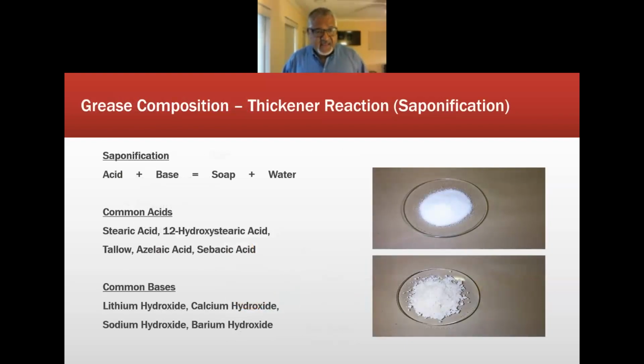Basically, I just want to describe the saponification process. You add an acid plus a base, and you end up with a soap. Oh, look, there's water as a byproduct, then we dehydrate the grease. The common acids that we use are stearic acid, 12-hydroxystearic acid, tallow, azelaic acid, sebacic acid. Common bases: lithium hydroxide, calcium hydroxide, sodium hydroxide, barium hydroxide. We're talking about conventional greases here.